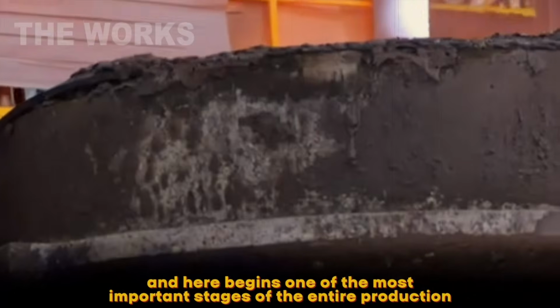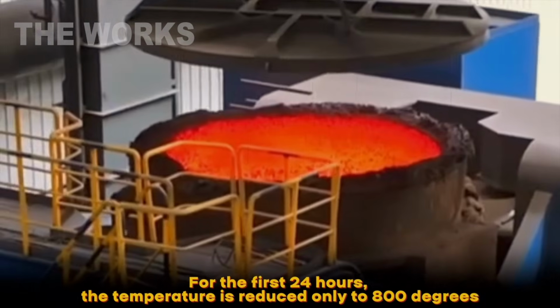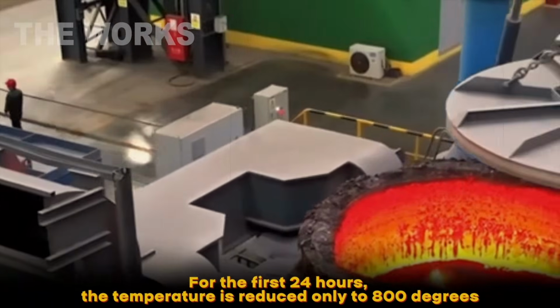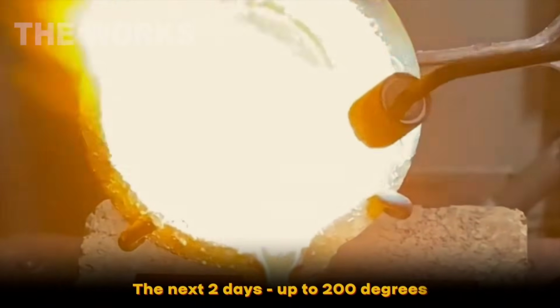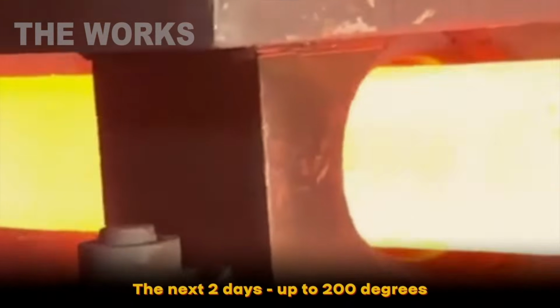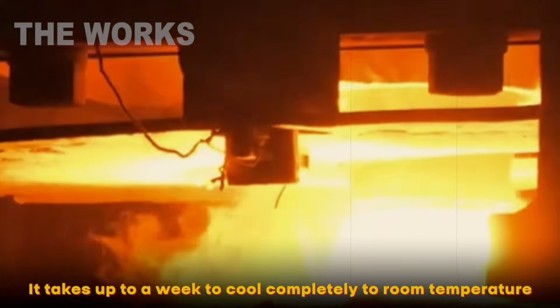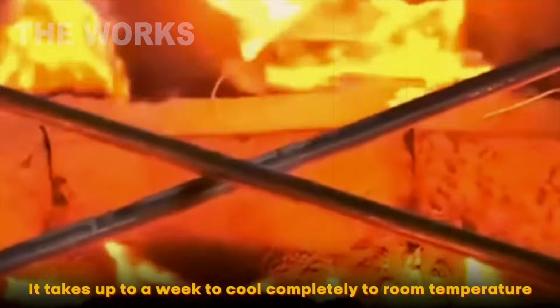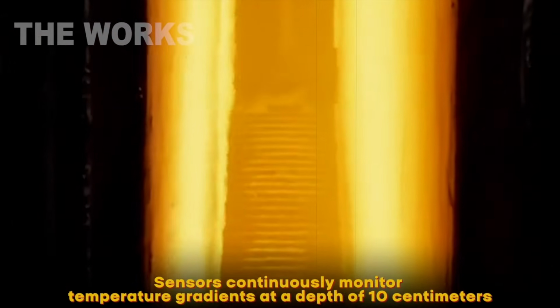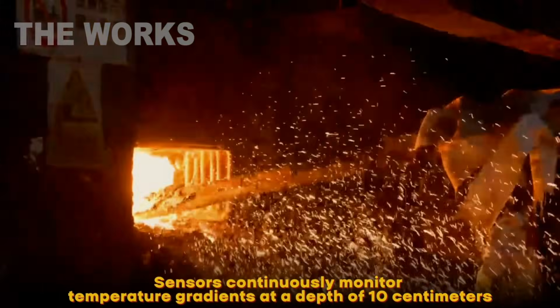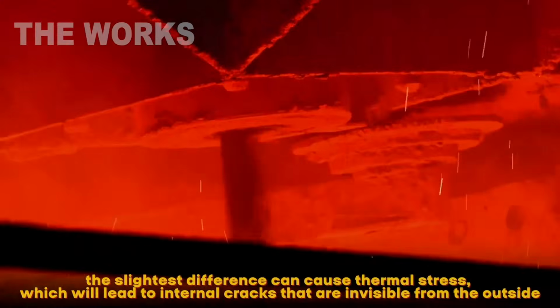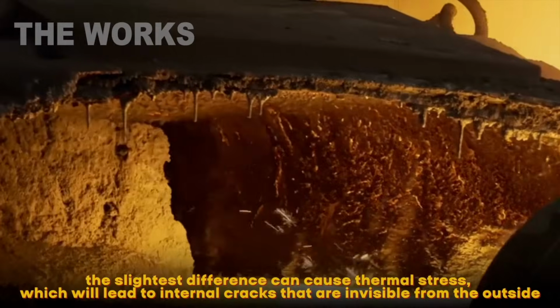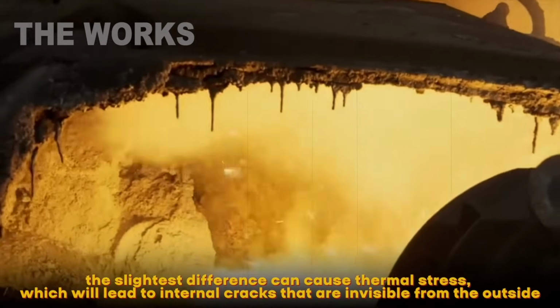For the first 24 hours, the temperature drops only to around 1,500 degrees Fahrenheit. The next 2 days, down to 400 degrees. Full cooling to room temperature takes up to a week. Sensors continuously monitor temperature gradients at a depth of 4 inches. The slightest variation can cause thermal stresses that lead to internal cracks, invisible from the outside.